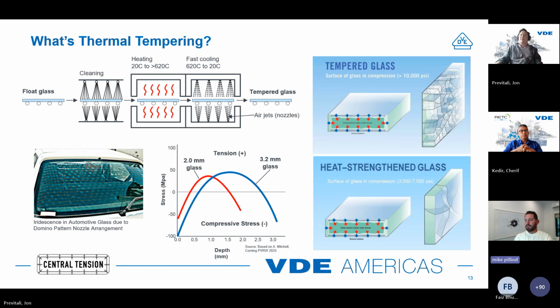And this is a property called fragmentation. But usually, and it's not binary, the more stress you have in there, when you break a fully tempered piece, typically thicker, it will end up in these fragments, which are non-sharp shards, so they are like shards in the industry. But that typically is for thicker glasses in general to get that breakage pattern.